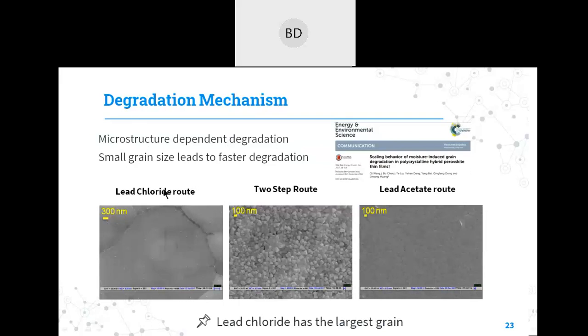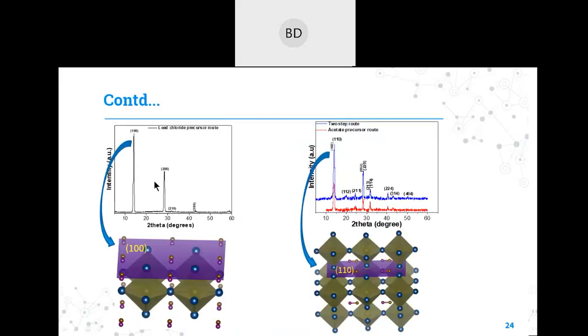The lead chloride route films was showing very good grain size ranging around 1 micrometer. But in case of two-step and lead acetate route, the grain size was small, it's around 100 nanometers. So ideally, if you go through this theory, this route should be degrading very slow and this should be degrading very fast. But in our case, this is degrading very fast and this is degrading very slow. So it means that there is something more happening than the grain size. So to understand this degradation process, we have closely observed the diffraction patterns of these three films.